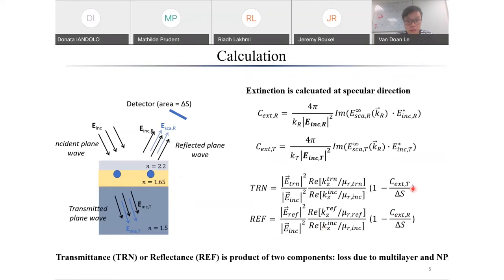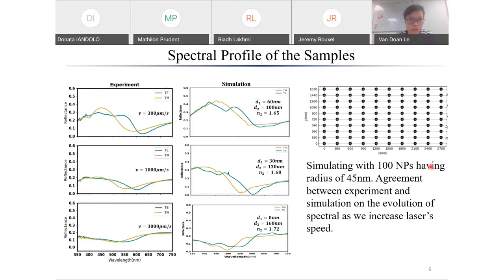Actually, it is the product of two components. The first one is the multilayer, where I just use the transfer matrix method to calculate the multilayer, and the second part is due to the presence of the nanoparticles. So this is the result of the reflectance, experimental and simulation, that I calculated. I keep the organization as on the top left of the PowerPoint file, as you saw. I simulate 100 nanoparticles with a grating period of 300 and a size of 90 nanometers. And I just change the thickness, as I mentioned previously, of the top layer and the intermediate layer, and you see the result matches quite well, even changing just the thickness.